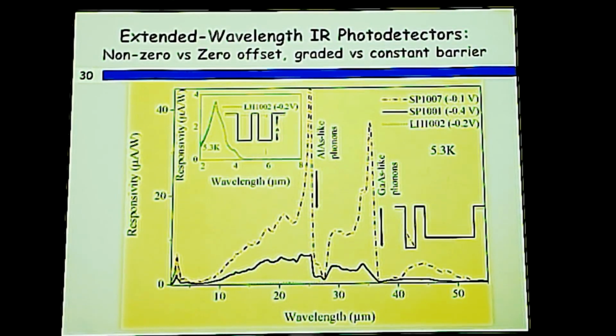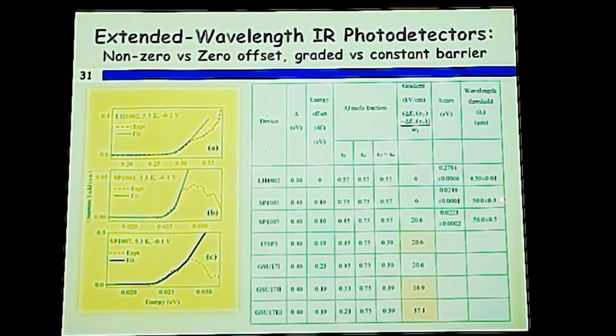So these are the results. Without the offset, there is no extended mechanism. However, the device with constant barrier but with offset has an extended wavelength mechanism, and with the gradient, that photoresponse becomes stronger. And the overall shape in both cases appears to be the same, meaning the mechanism appears to be the same in both devices. The wavelength threshold, obviously the reference device has in mid-infrared. SP1001 has 50 micron or so, SP1007 56.